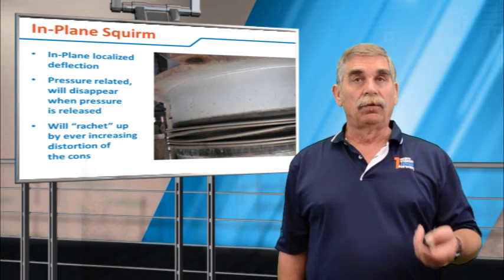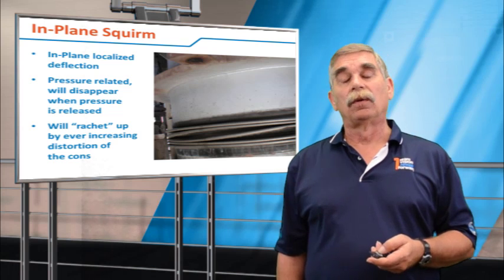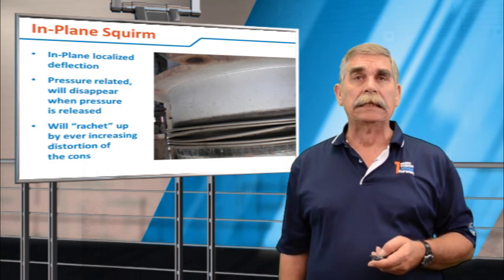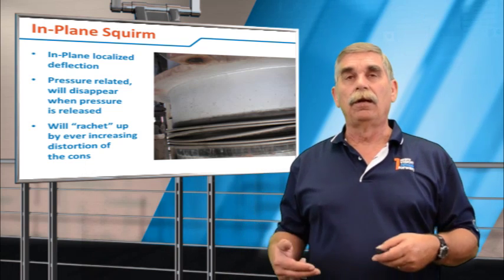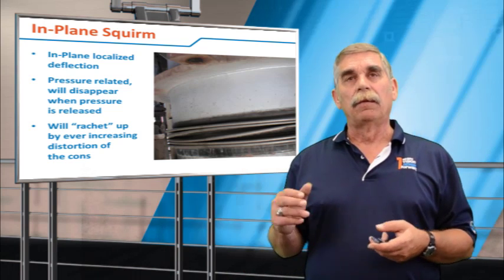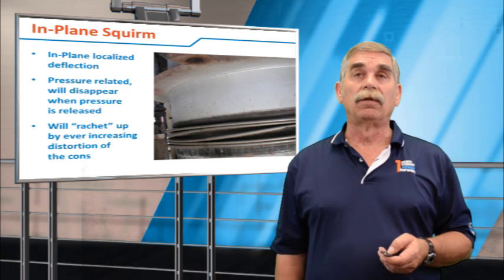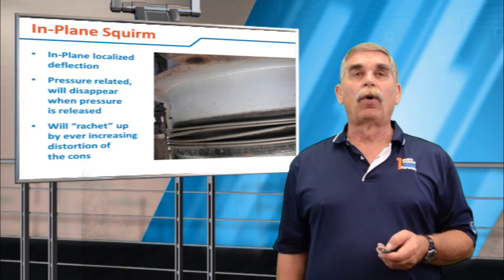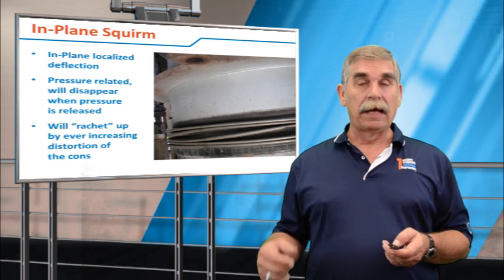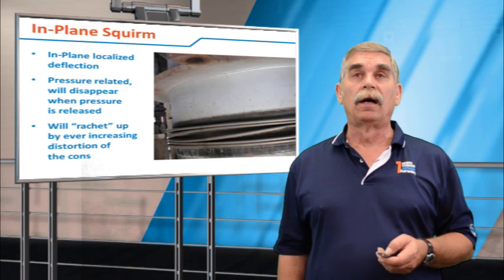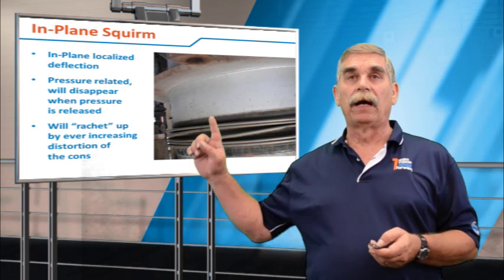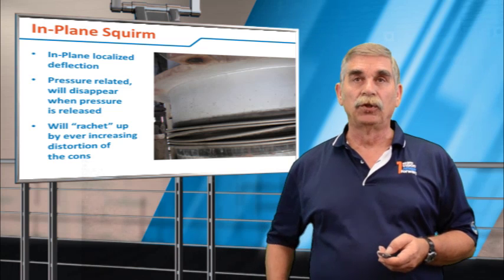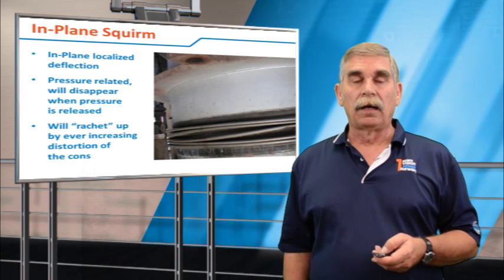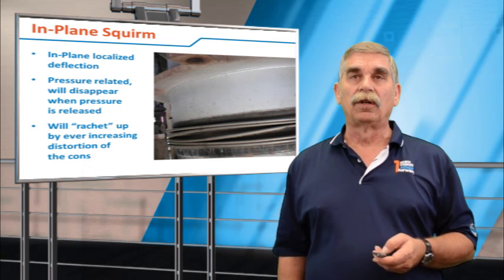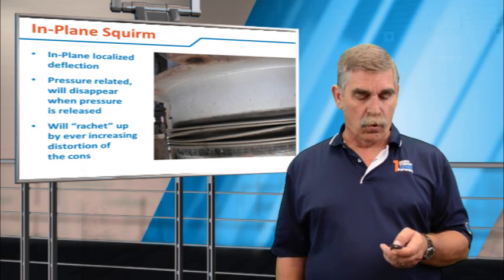And the problem is that when you come down, the convolutions will revert back to the neutral position, or the normal position. That will continue, but each cycle, the amount of instability in the convolution will increase to the point where you'll ratchet up and form an inflection point on the convolution. You can see right here the dimple in this convolution. Now that dimple will continue to get worse and worse until you have a failure at that point.